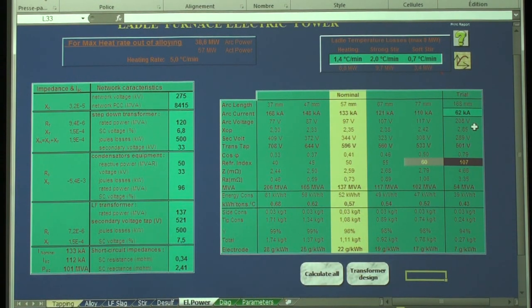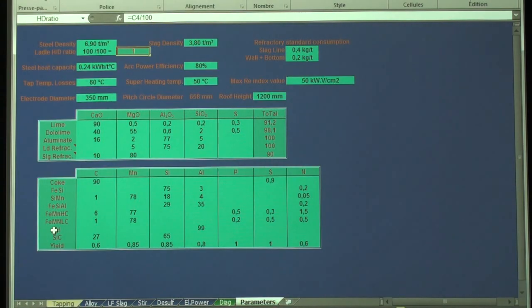So you will have to increase the transformer tap to 500 volts. Of course, you will need 50 MVA plus 5% or 10%. You design the current for the normal case, and you increase the number of taps. You increase the voltage in order to get the power you need for 5 degrees per minute. But in this case, maybe I have to change the arc efficiency because it's going to be a long arc.